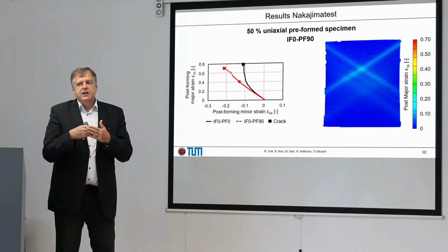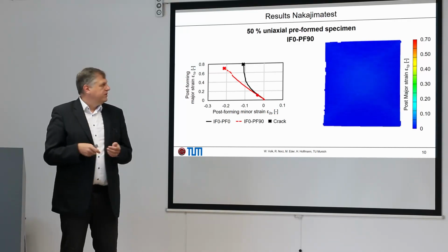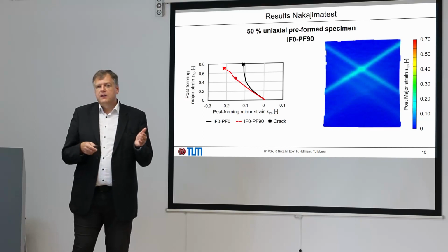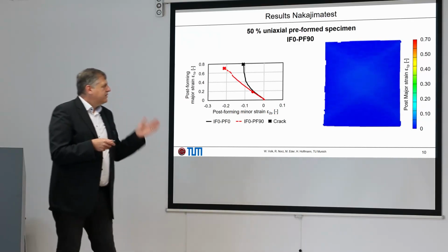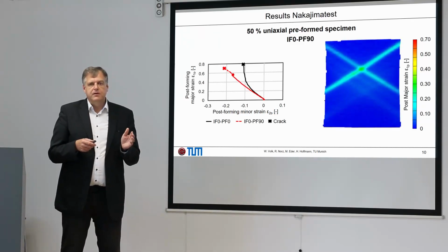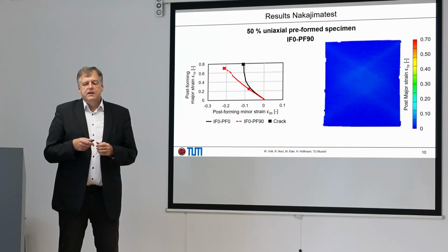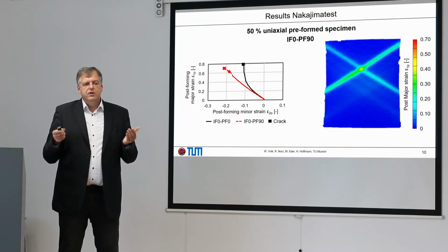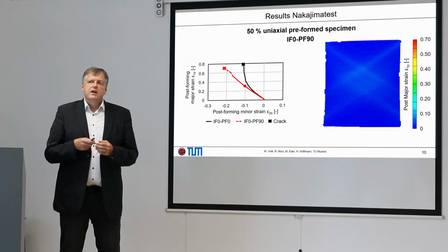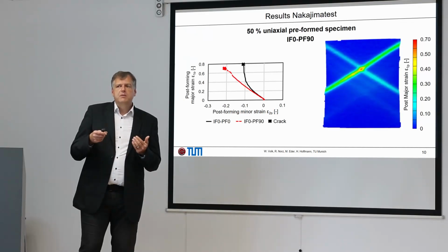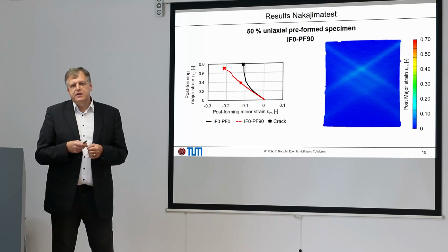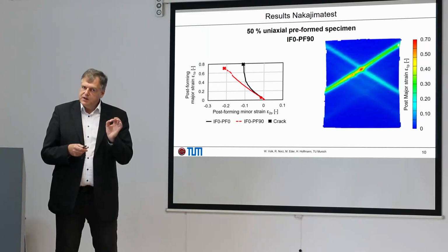So we see directly no change to plane strain, and like a smooth, ductile shear fracture. So also in comparison to the classical one, no start out of the specimen mid, and really a totally different strain behavior, a little bit comparable to materials with a negative strain rate sensitivity, which is here not the case.